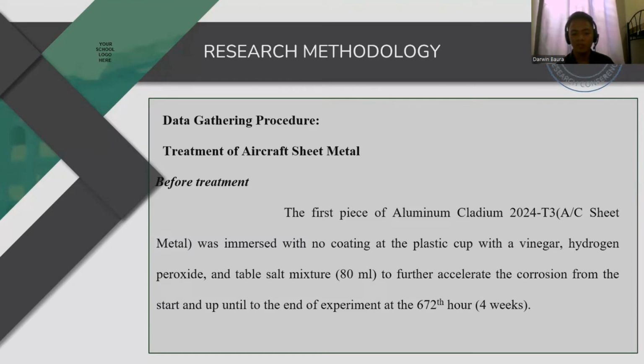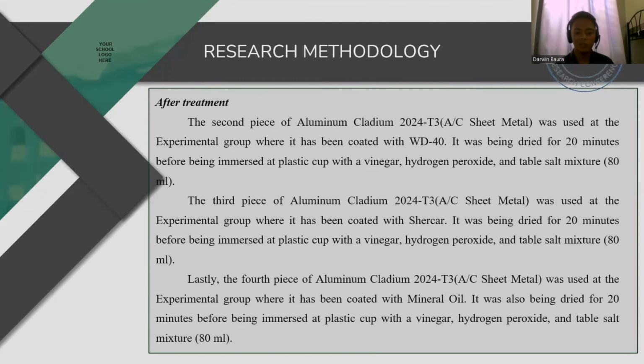So the first piece of aircraft sheet metal was immersed with no coating in a plastic cup with a vinegar, hydrogen peroxide, and table salt mixture up until the end of the experiment, or the second time point, 672 hours. Same goes for the after treatment. The second piece of aircraft sheet metal was coated with WD-40. The third piece was coated with Shercar. And lastly, the fourth piece was coated with mineral oil.